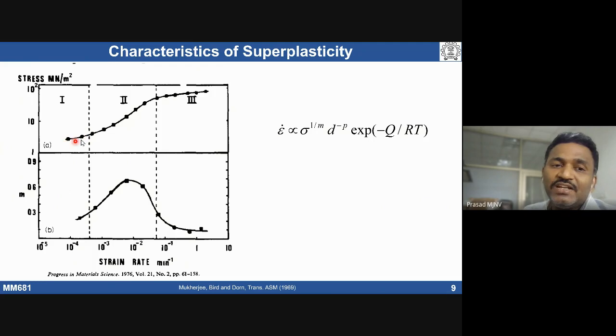Region 1 is basically a low m value. Similarly, region 3 also has a low m value. But region 2 has a higher m value. That's why region 2 is the superplasticity domain. If I want maximum ductility, I need to deform the material at this strain rate, which gives this much stress at a given strain. So this is the domain where the material is going to show superplastic behavior.